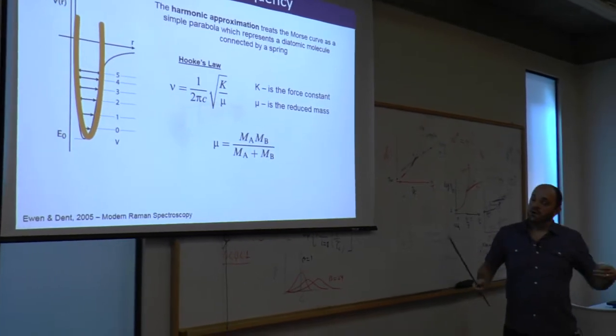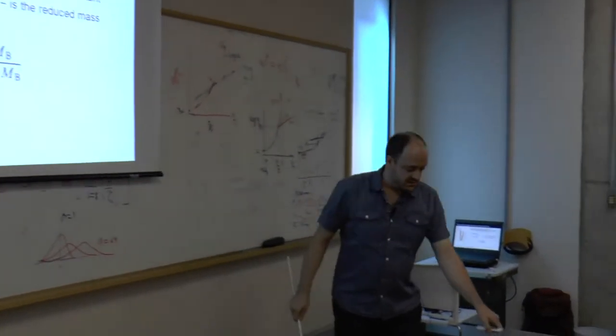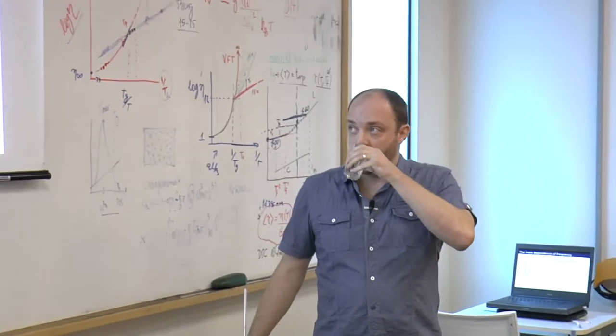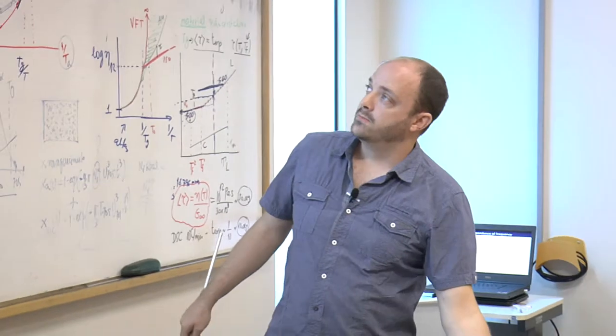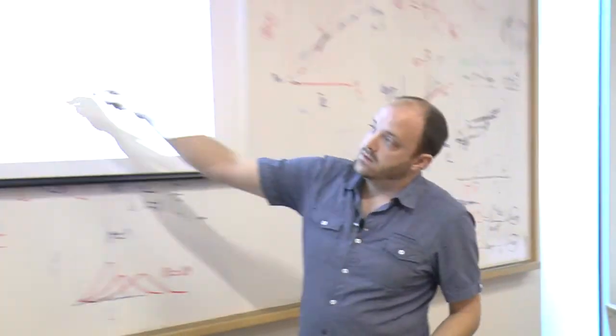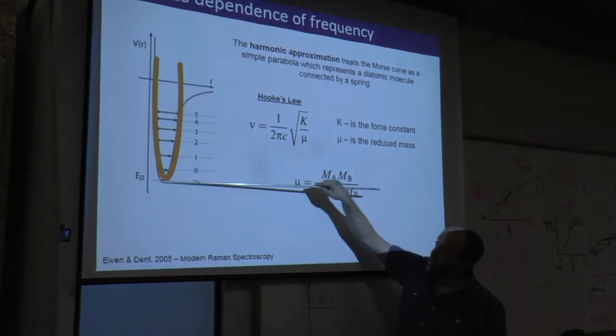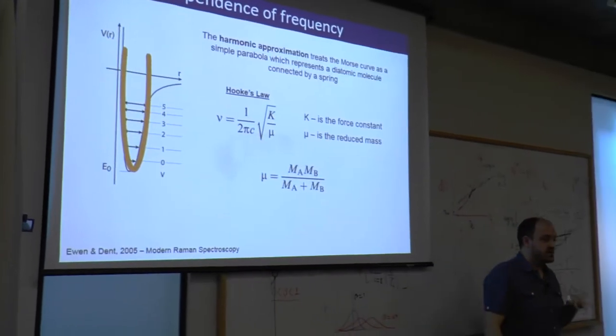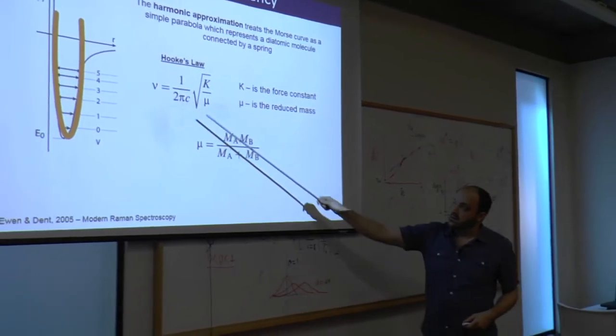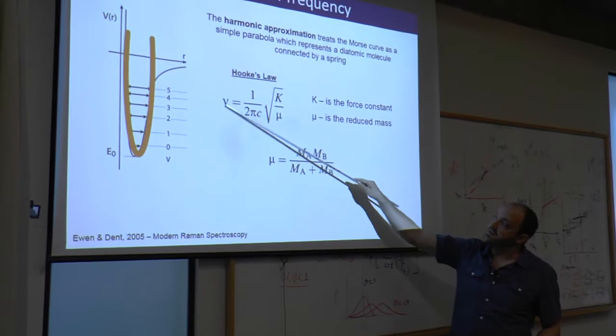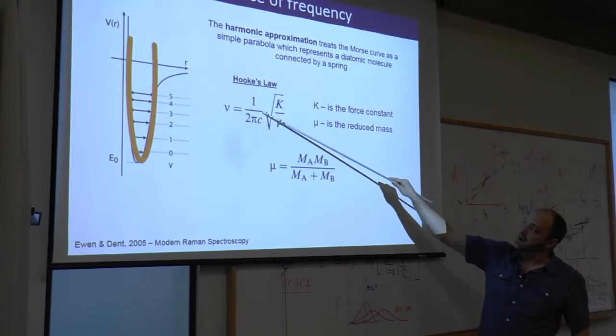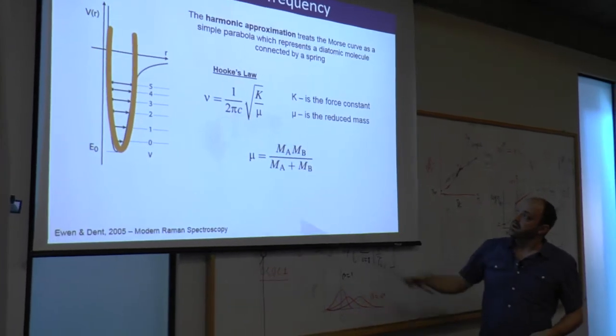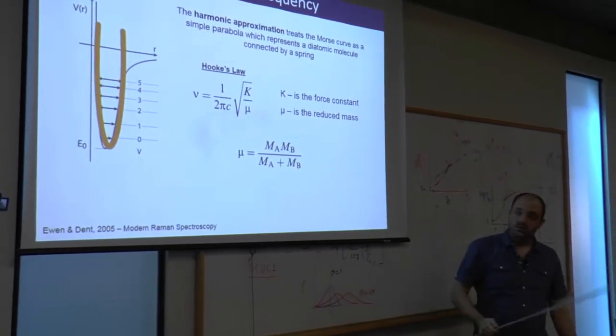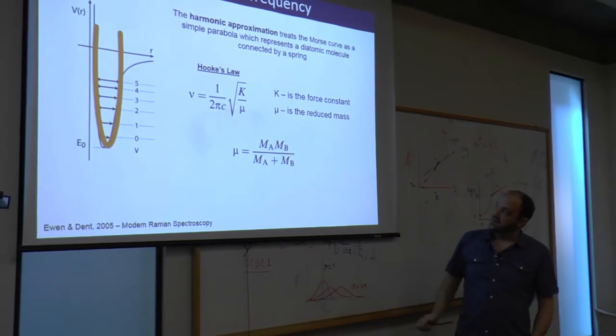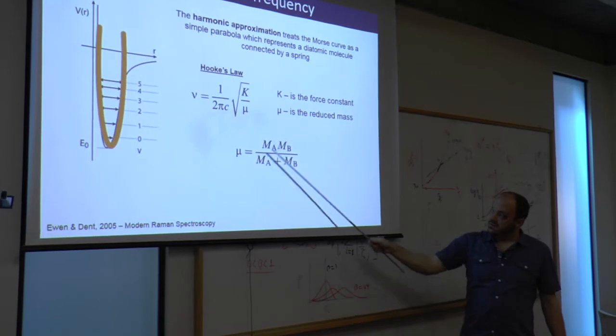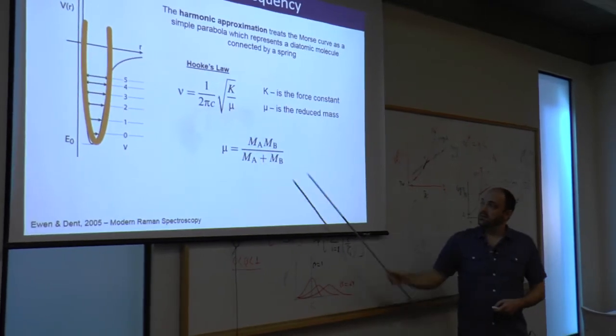One of the ways we model what these vibrational frequencies are is using the harmonic approximation. In the harmonic approximation, we treat this Morse curve as a simple parabola. And most of the time, this works very well. Here we use Hooke's law, which states that the frequency is related to a bunch of constants times the square root of k over mu. k is the force constant, the strength of the bond, and mu is the reduced mass, which is given here: the mass of atom A times the mass of atom B divided by the sum of those two.